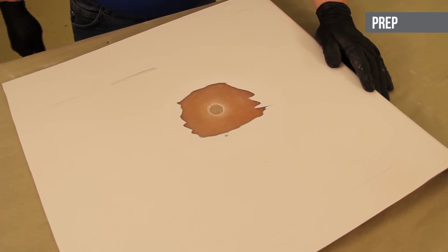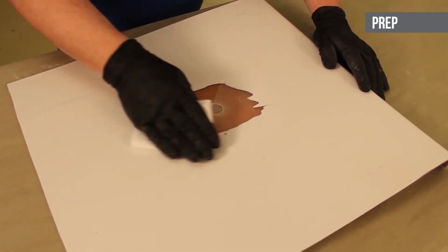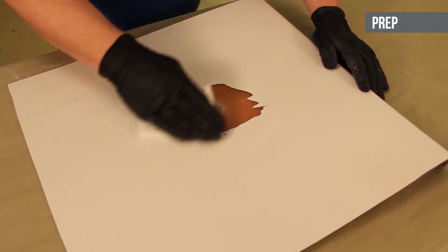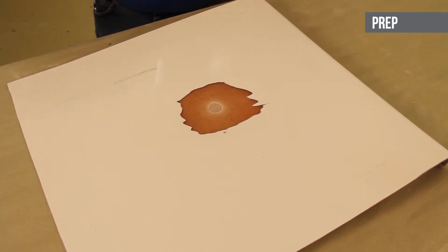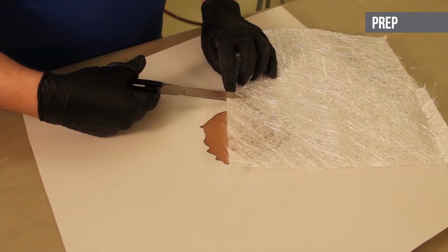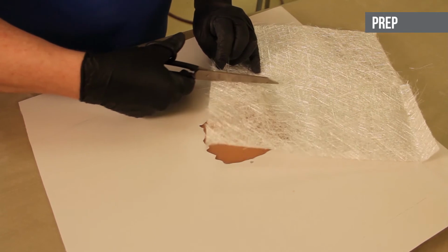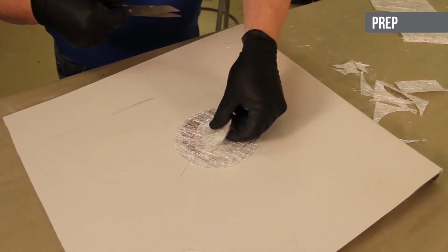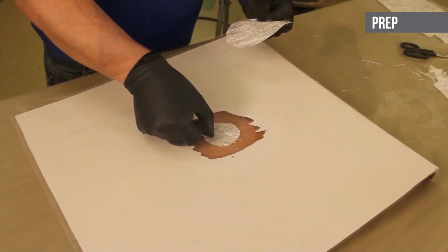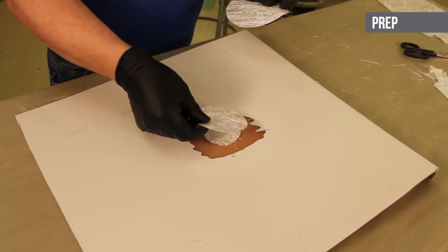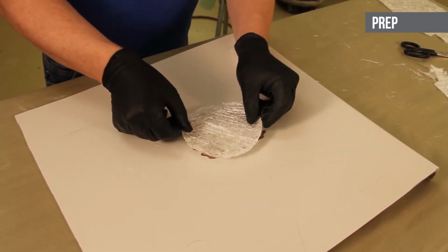Remove dust and clean the area with the prep wipe. The surface must be completely clean and dry before applying the fiberglass resin. Cut the fiberglass mat to overlap the repair area by at least 2 inches. If applying multiple layers of mat to strengthen the repair, make each layer slightly larger than the last.